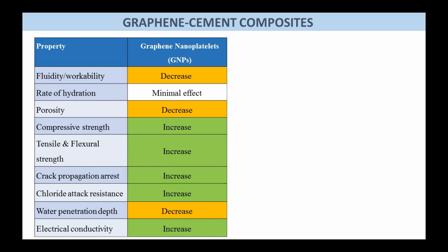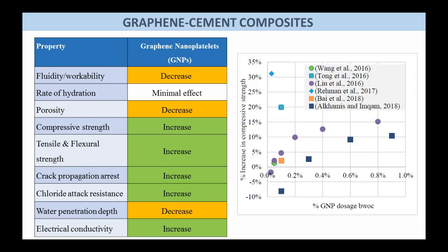And very importantly for me and my self-sensing is that the electrical conductivity increases significantly when you mix graphene in your concrete. However, the challenge in the literature is that authors use different percentages of graphene. They get different percentage improvements in strength. And even if people use 0.3% graphene, let's say, some people found a 5% increase in strength, and other people found a 10% decrease in strength. So there is still not a definitive answer as to how much graphene you need to add in concrete and whether that graphene has a beneficial effect, especially in terms of strength.